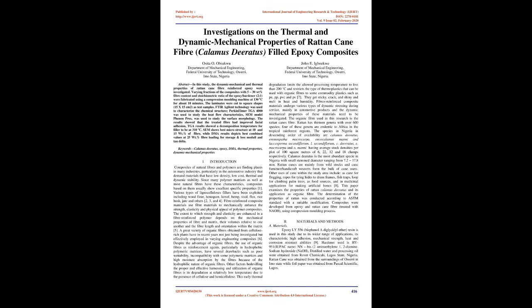TGA results showed a decomposition temperature for the filler to be at 310 °C. SEM shows the best microstructure at 10 and 15 wt% of fiber, while DMA results depict the best combined values at 25 wt% fiber loading for storage and loss moduli and tan delta. Keywords: Calamus deeratus, epoxy, DMA, thermal properties, dynamic mechanical properties.